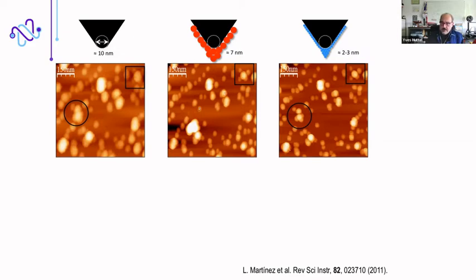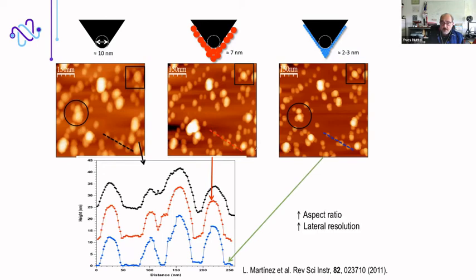And as you can see, the resolution improves significantly. While with the commercial tip with 10 nanometer diameter, you can hardly see the details of these two objects. With this tip covered by small nanoparticles, you can make the distinction between these nanoparticles that form agglomerates. And if we make a profile, we can even much better see that with the tip covered by the smallest nanoparticles, we can resolve much better the structures and even go down to the flat silicon substrate. So we have increased lateral resolution by coating these commercial silicon tips by nanoparticles.